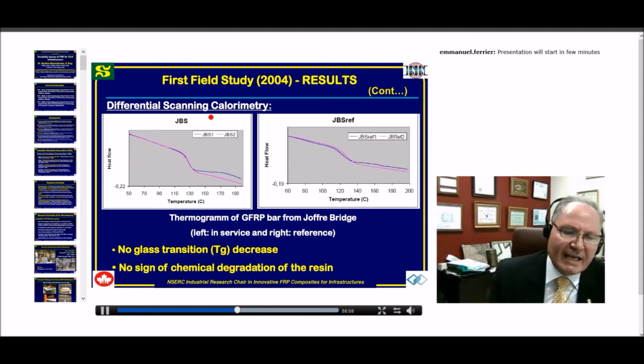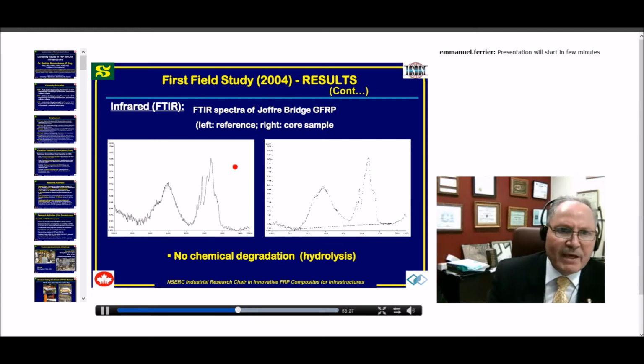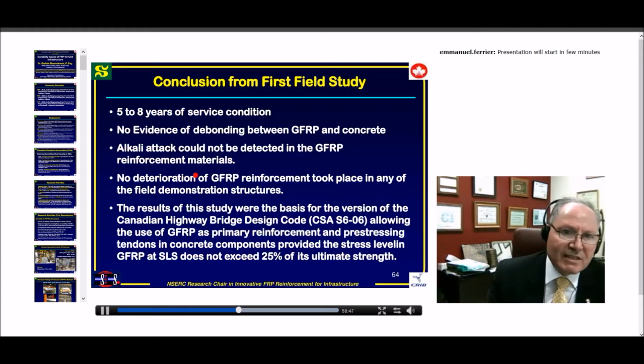Also about DSC, we compared the reference specimen, as you know, on the right, and this is the in-service one, and you can see they are quite similar, which shows no sign of degradation of the resin. This is the infrared spectra from Joffre Bridge, and if you compare this curve to this curve, it's the same thing. So they show no chemical degradation, which would be the hydrolysis. So from this, we come up with this conclusion.